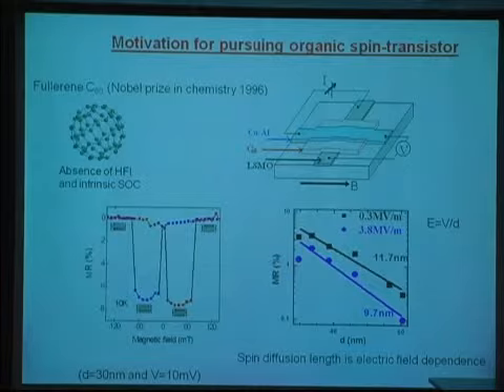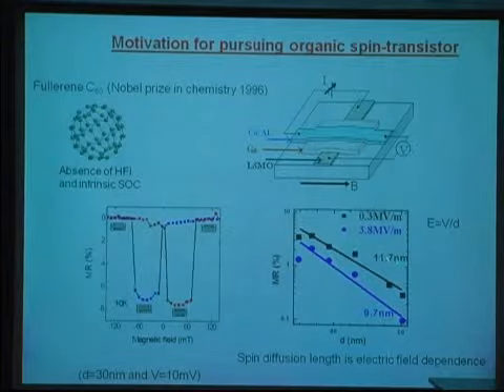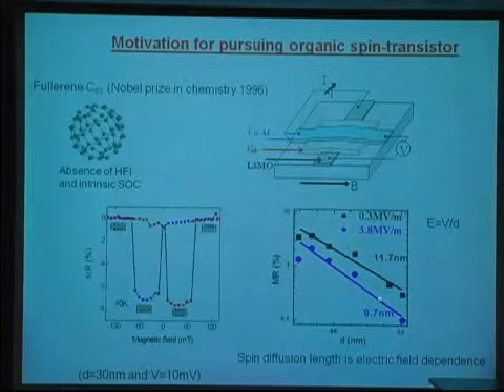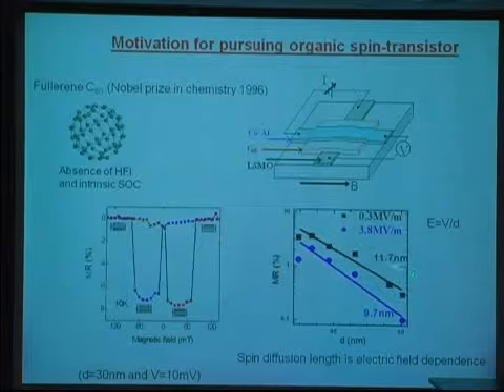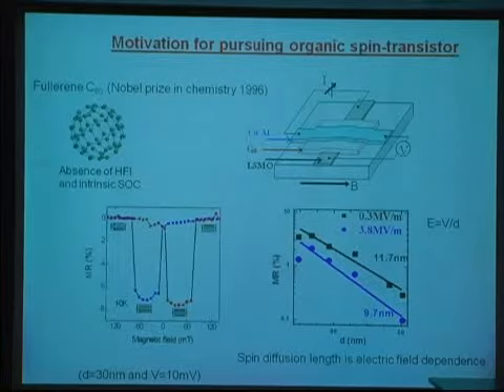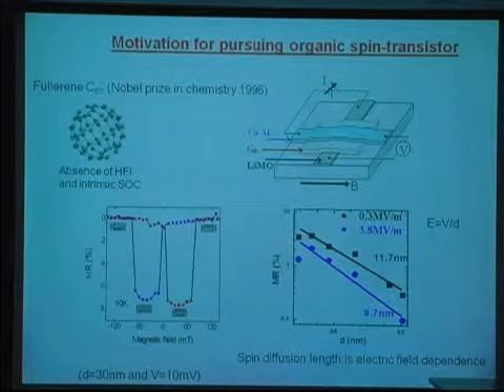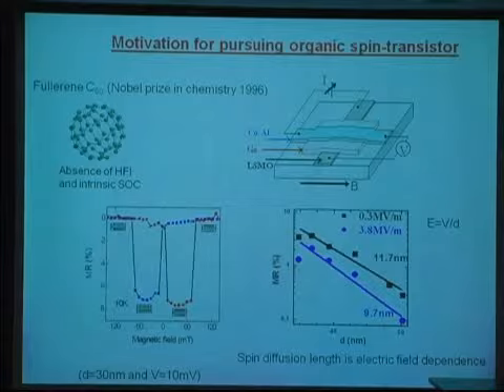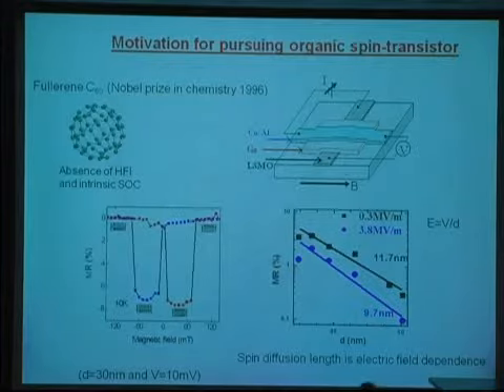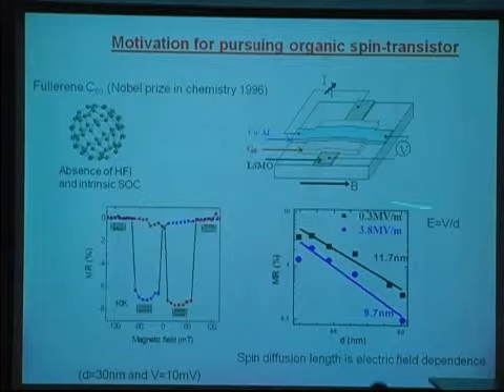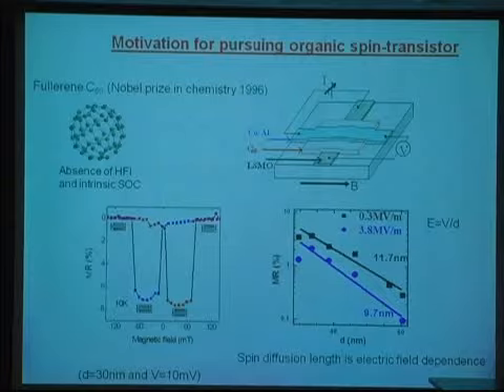Actually, we don't understand, we don't know, but we measure the spin diffusion length versus the applied electric field. And we actually see that there's some change in the diffusion length here. So the spin diffusion length actually depends on the electric field. We don't understand why, but this is the experimental result. And the stronger the applied electric field, the shorter the spin diffusion length. And this encourages us to go for the spin transistor. So we hope that we can change the spin diffusion length if we apply a stronger electric field than this, because here the electric field is not very strong actually. So this is our motivation that we might achieve the spin field effect transistor if we use organic materials.